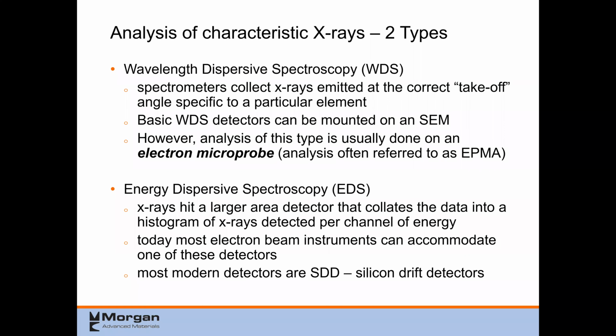Energy dispersive spectroscopy, on the other hand, is where you basically collect all the X-rays at one time. They get binned according to the energy, and you look at a histogram of X-rays detected per channel of energy. Most SEMs today have some sort of EDS on them, unless you're just doing plain imaging. But the basic way to characterize your material is to have an EDS mounted on an SEM.